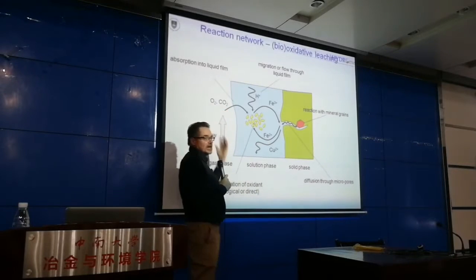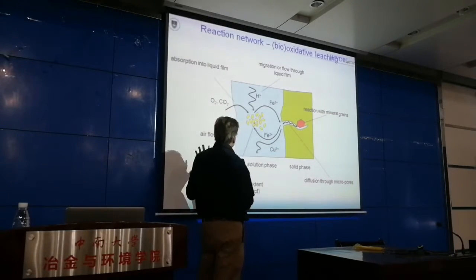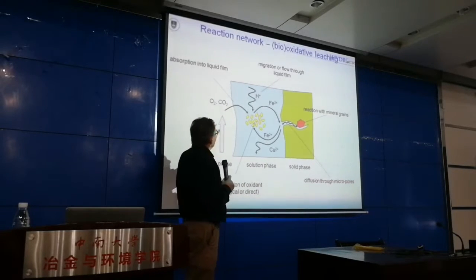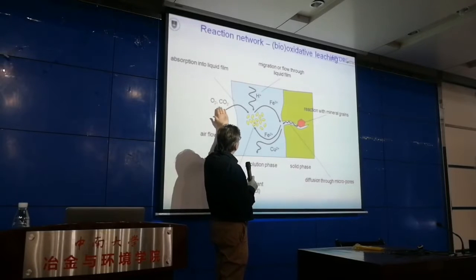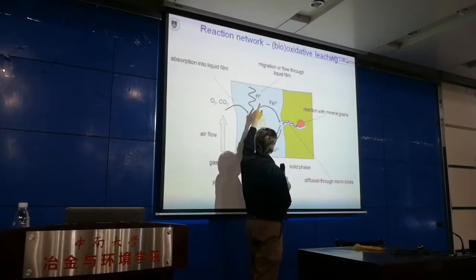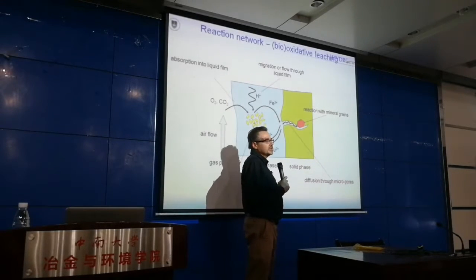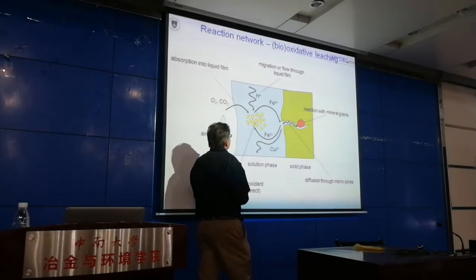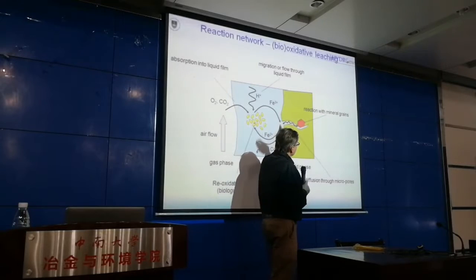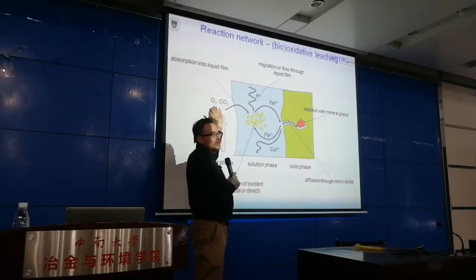The oxygen has to come from the gas phase. And so we need good contact between the solution and the gas phase in order to facilitate the transfer of oxygen into the liquid phase to facilitate the oxidation of ferrous back to ferric iron, which can then migrate into the mineral grain. You could, of course, argue that oxygen could itself migrate into the pores, but, as I'll show you a little bit later, the solubility of